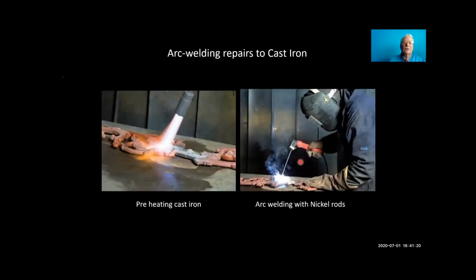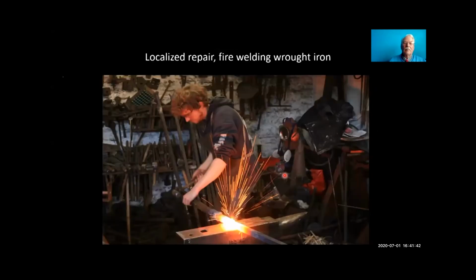I mentioned hot work on castings. You can preheat cast iron and then arc weld with often nowadays nickel rods, but I personally, in my consultancy, only ever recommend this for non-structural applications. This is fire welding, where you heat up the two ends of wrought iron, only for wrought iron. You can do it with steel, but not cast iron. You heat up both ends white hot and hammer them together.